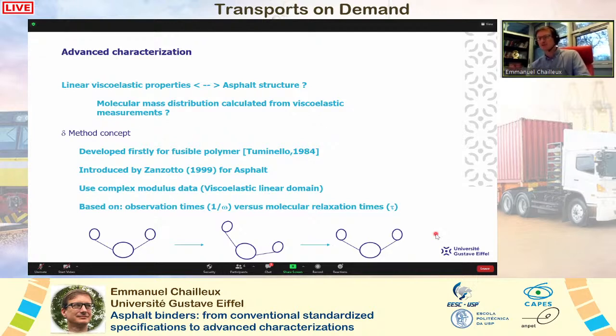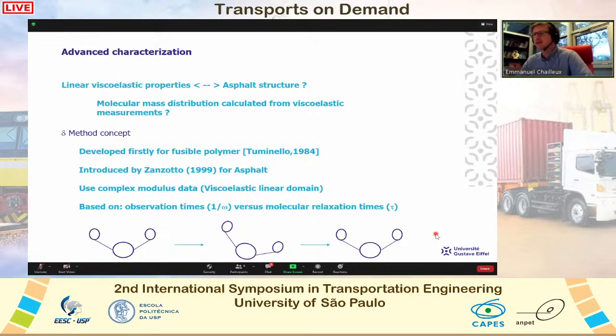from viscoelastic measurement. So this method was first developed for fusible polymer, and it was first introduced by Zanzotto, an asphalt specialist, some time ago. This method uses complex modulus data, of course measured in the linear domain, and the main concept is based on the comparison of observation time versus molecular relaxation time.